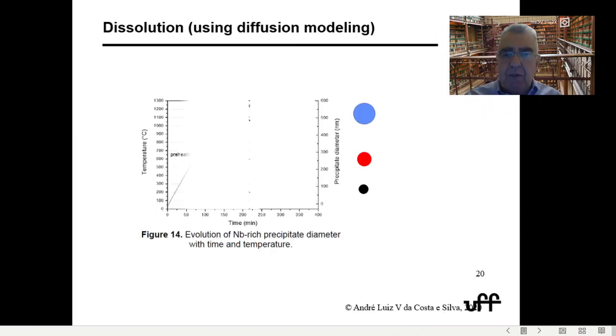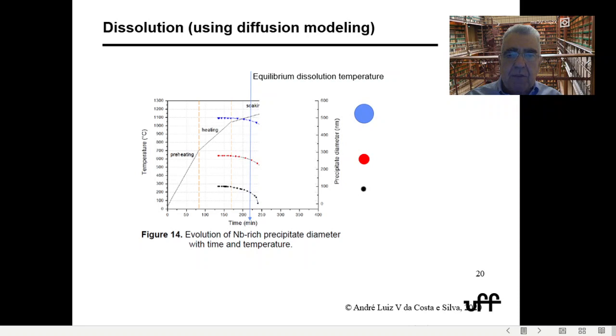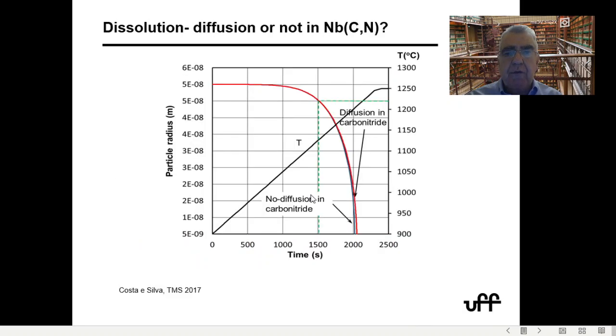And this is just the same, but a little animation. When you reach the equilibrium dissolution temperature, then you have some particles dissolving completely, the small ones. Then if you continue, you have the medium ones, and then if you want to dissolve a half a micron size particle, you need more temperature and longer time. So this is what you have to do when you design your process: you have to know what happened during solidification, what kind of carbonitride you still have in medium to large size, what is lost and what is not lost. So if you assume that half a micron is the size of carbonitride that you want to dissolve, you can fairly well design your plate heating to achieve that.